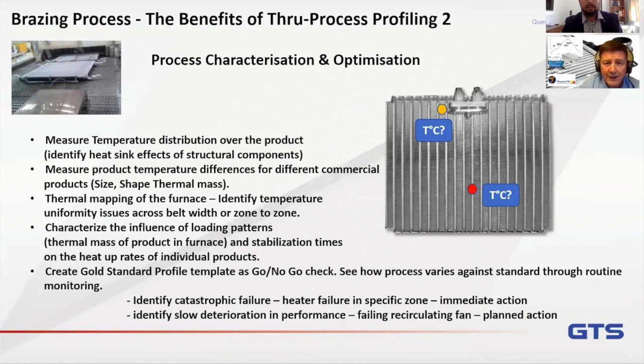So on the drawing or the image in front of us now, you can see two positions of thermocouple placement. One's yellow and one's red. Now you can see the yellow thermocouple is close to a structural component of the radiator, which looks relatively bulky. So when you're thinking about putting your thermocouples on the radiator, look for areas where there may be significantly more metal or more mass, because more mass will generally create a slower heating rate. So you're looking for areas of concern. Don't just simply pick uniform positions on the product, because you will then get an easy solution to your profile. Look for the challenges, because that's where you're going to end up with the product problems.